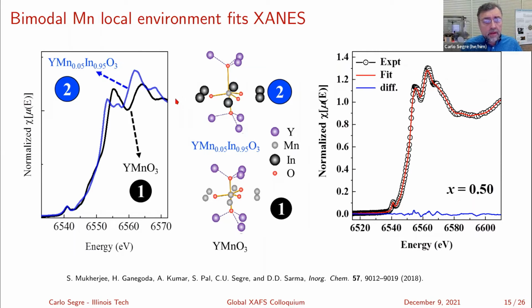So once we decided that, we decided, well, let's see if we can do some fitting of the XANES only. We took our endpoints of XANES and we fit all the intermediate XANES patterns. And in fact, we get extremely good fits. We can fit every one of them with a simple linear combination of these two endpoints. Now it's 5%, so it's not as dilute as maybe I'd like it to be, but it's still quite close to being dilute. It's 1 in 20 unit cells, which is okay. That's not too bad. I'm showing here the x equals 0.5. You can see it's really quite a good fit. I usually don't see this good a fit with XANES, and all of them were basically fit like that. I'm just showing this one as an example.